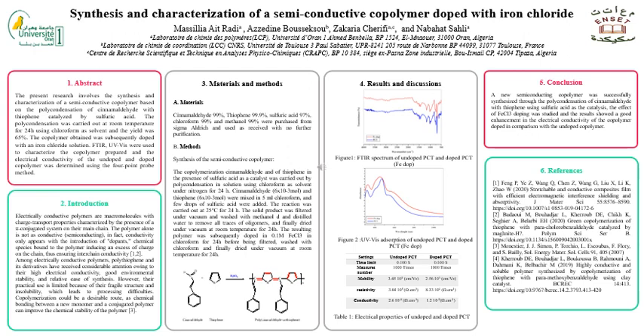According to the infrared spectra illustrated in Figure 1, both doped and undoped copolymers exhibit an absorption band at 1681 cm⁻¹, which is the characteristic band of the carbon double bond, proving that both copolymers have a π-conjugated structure and confirming the success of the synthesis process. For the doped polymer, a new absorption band appeared at 573 cm⁻¹, which can be assigned to the formation of a complex between iron chloride and the semiconducting copolymer.